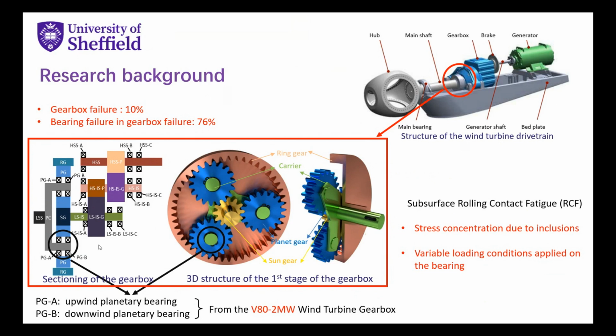Based on our investigations, we found that subsurface rolling contact fatigue, or subsurface RCF, is very important to this premature failure of the bearing. We also found there are 2 reasons for the rolling contact fatigue. The first is stress concentration caused by subsurface inclusions. The second is related to the loading applied on the bearing, since overloading cases may accelerate the subsurface rolling contact fatigue and cause premature failure of the bearing.